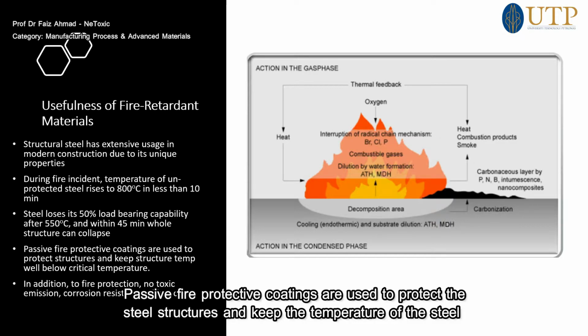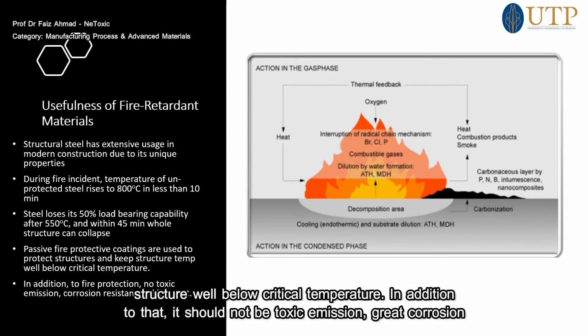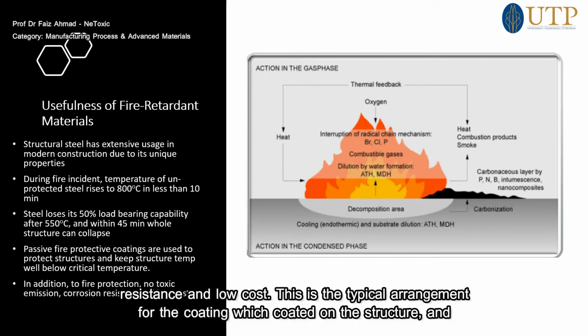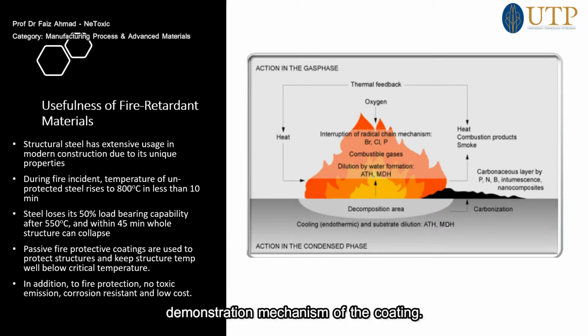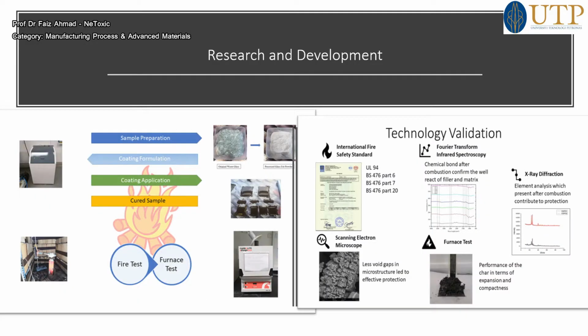Passive fire protective coatings are used to protect the steel structure and to keep its temperature well below the critical temperature. In addition to that, there should not be toxic emission. It should be corrosion resistant and low cost. This is a typical arrangement of the coating which is coated on the structure, and the degradation mechanism of the coating.